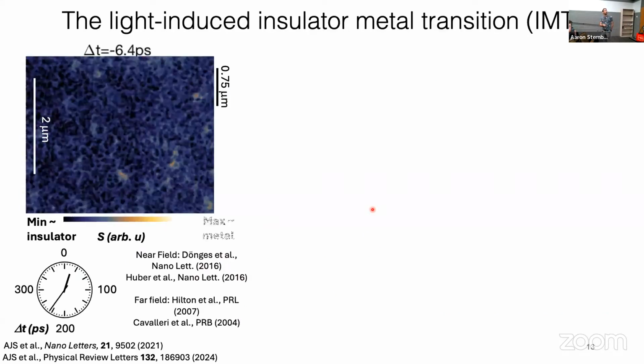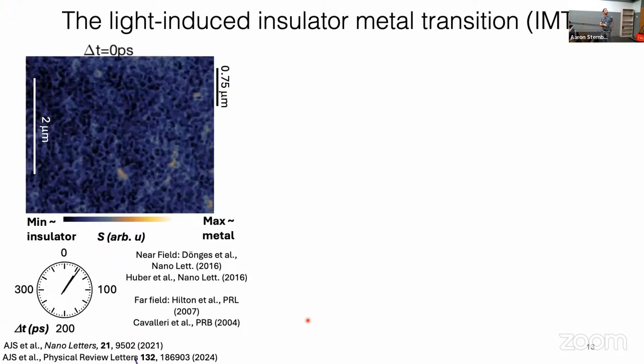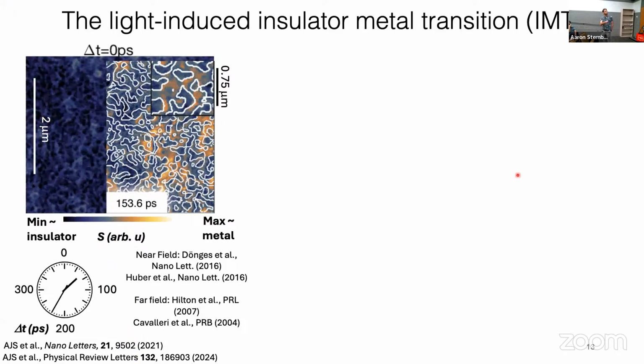In the light-induced transition, we compared the conductivity to features that are observed in the AFM topography coming from grain boundaries in our film. And these grain boundaries have perimeters that are highlighted by the white lines. What we can see is that the largest amplitude of the near field signal in the transient state tends to appear in between the grains. So we see the strongest enhancements of conductivity in the transient state at grain boundaries.